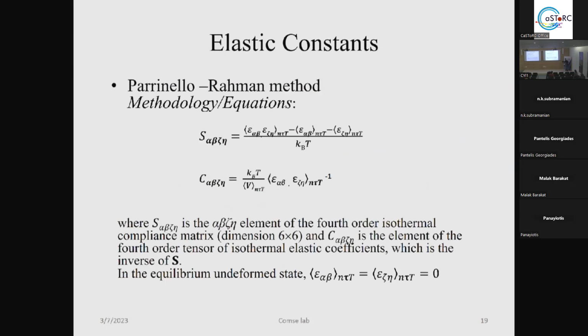As regards the Parrinello-Rahman method now, we try to calculate the compliance matrix through the strains of the system in the equilibrium undeformed state for more than 70 nanoseconds of molecular dynamics equilibration run. In that case, these two parts go to 0 because of the undeformed equilibrium state, and thus the compliance matrix takes that form and is more elegant and easier to solve.